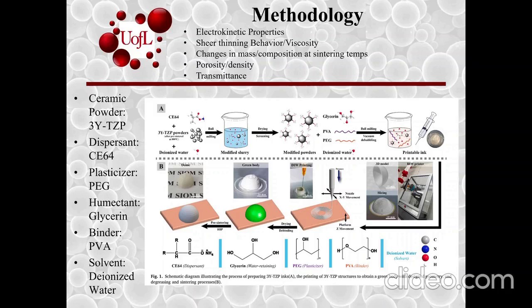But what did they test after they created this ink? Well, that is what is shown in the top bulleted list at the top of the slide. They tested electrokinetic properties, shear thinning behavior, viscosity, and changes in mass or composition at the different sintering temperatures. They tested porosity and density, and lastly transmittance, because the whole point of this project was to see if they could create an IR transmittant ceramic powder. So that was tested.